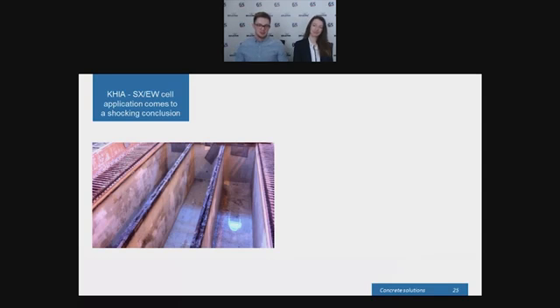What they had was they removed the copper ore out of the mine, and you find that you've got the copper in with lots of different impurities. In order to extract this copper, they dissolve it into sulfuric acid. Obviously, introducing sulfuric acid into concrete is never a fantastic idea. Over time, it will break down and wear away. So the 2 problems they faced with this: one was the sulfuric acid, and the second was that they had this sulfuric acid mix at 50 degrees centigrade. So it's not a cold mixture either.